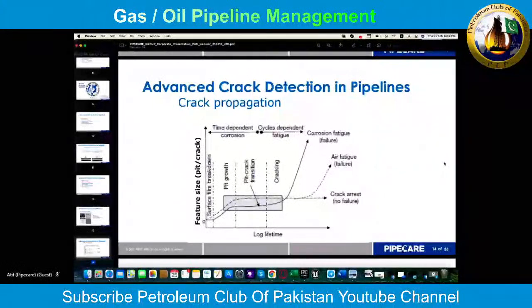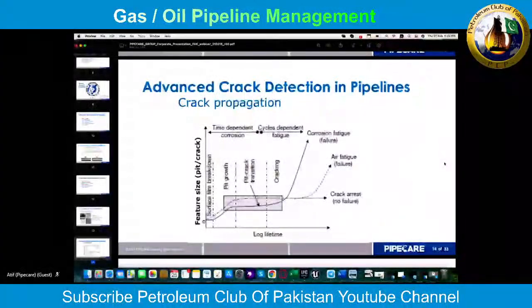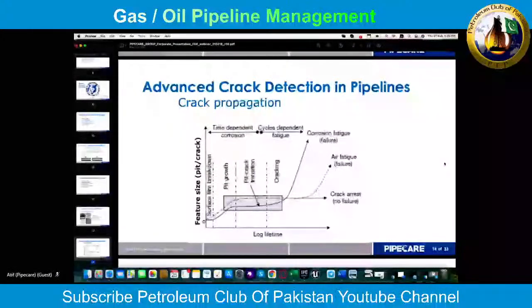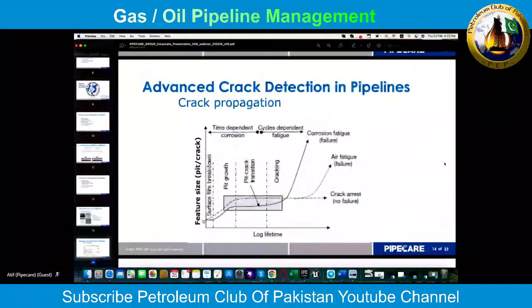What can be said as a general rule is that pipelines which are susceptible to cracking very often develop cracks within the first 15 to 20 kilometers after a compressor or a pumping station. But this is only one of the indications which may be used to determine whether a pipeline is susceptible to cracks or not. But it can be kept in mind as a rule of thumb, where to start looking if a pipeline is under threat of cracking.